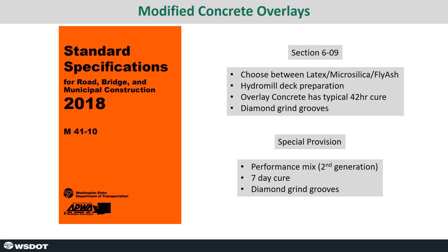Now, if we have an existing concrete overlay and we're starting to get into second generation, a lot of those concrete overlays that were put in in the early 80s are now almost 30 years old and requiring rehabilitation again. We've decided to use a performance mix similar to brand new bridges. We've tweaked the mix a little bit, so instead of a 14-day cure, we're doing a 7-day cure, and then we are doing the diamond grooves.